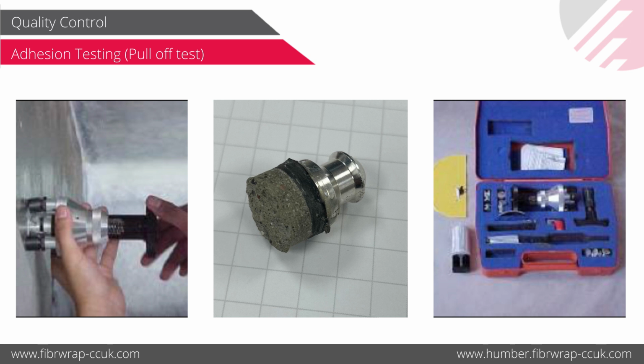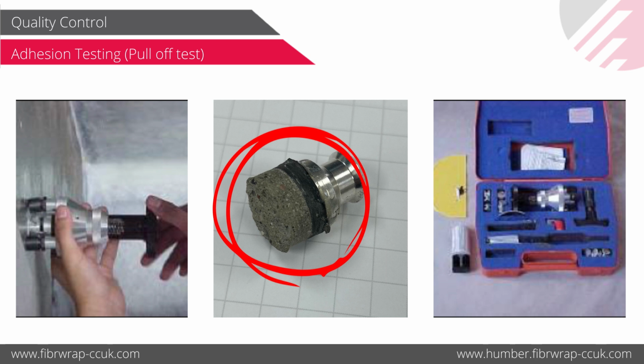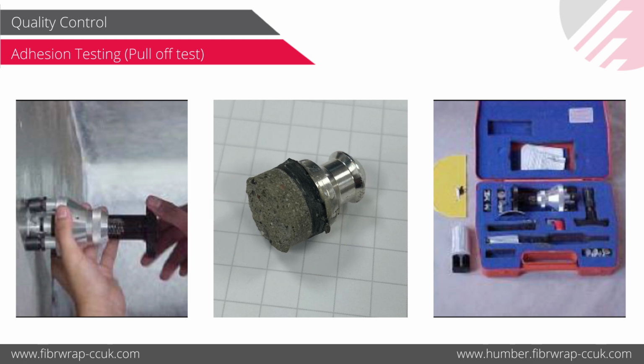So all we want to see is that when you do this pull-off test, it should not come off from the substrate only, or should not come off from another layer of FRP if there are multiple layers. So in the middle image, we could see that when they pulled it off, it took out some concrete with it, which shows that the bond between FRP and concrete is stronger than the actual concrete failure strength. So that's the pass criteria for the bond test.